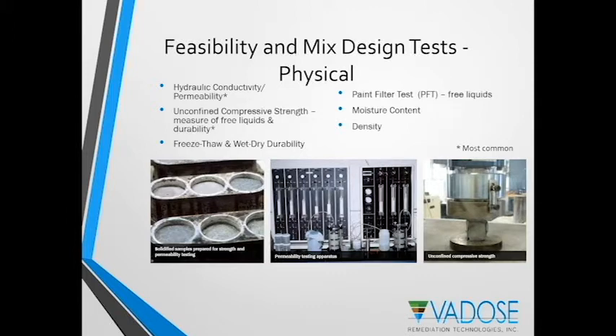Some of the typical tests that are done in the feasibility and mix design process include, for physical testing, hydraulic conductivity. That's the picture in the middle where you see triaxial permeameters measuring the rate of flux of water through that solidified sample. Also, we test unconfined compressive strength. Other tests that might be conducted include freeze-thaw durability or wet-dry durability, free liquid tests such as the paint filter test, moisture content, and density.